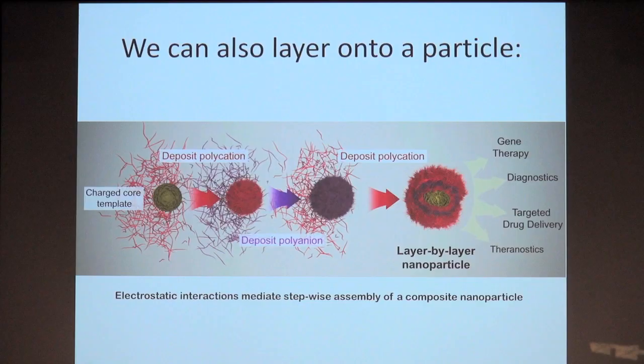Now, I've talked about things that are sort of big. Now I'll talk a little bit about things that are incredibly small. We talked about the size of nanometers, and these nanolayers are certainly along that range. It turns out that you can coat not only big things like implants with layer-by-layer films, you can also coat incredibly tiny things with the same kinds of layers. We can take a nanoparticle, a particle that is, let's say, 10 or 20 or 40, 100 nanometers in size, and we can, as long as it's charged, adsorb a polyelectrolyte of opposite charge onto that surface.